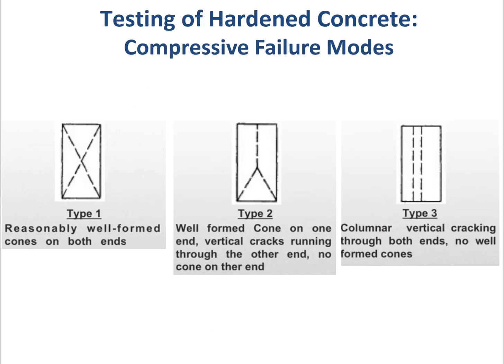There are 3 main failure modes. The first type is reasonably well-formed cones on both ends, which means the specimen fails in shear. The second type is a well-formed cone on one end and vertical cracks running through the other end, so no cone on the other end, which means the specimen fails in a combination of shear and splitting.